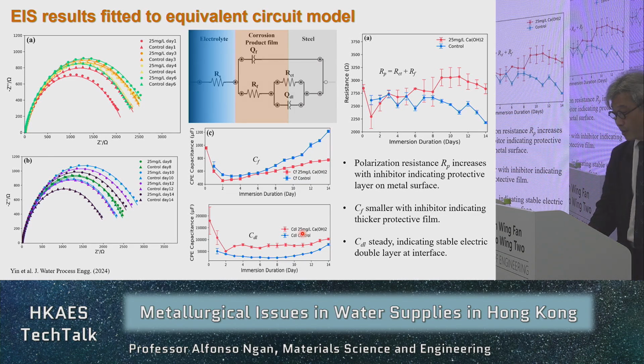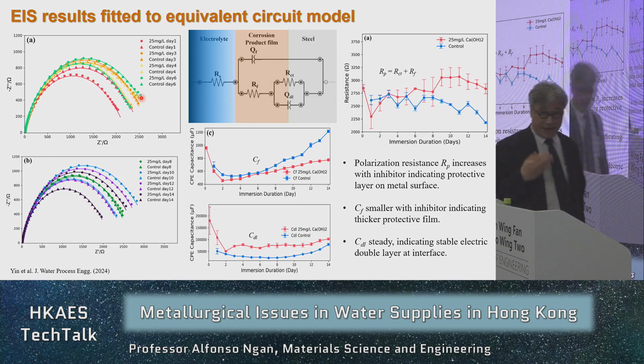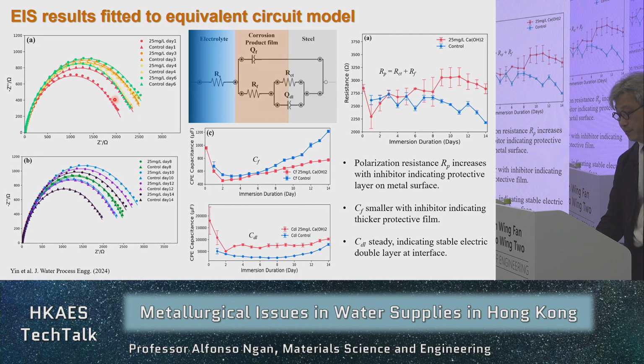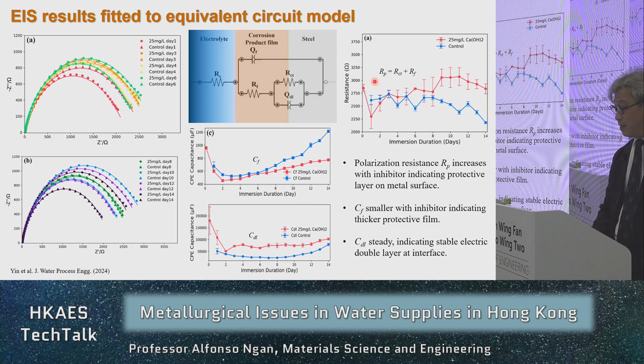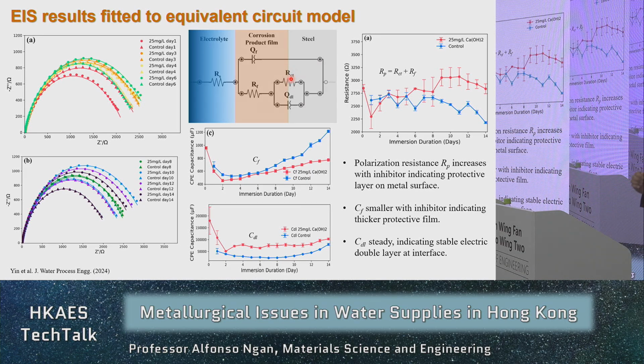Those are the real results from our simulated seawater test. So you see a lot of semicircles, but they are not exactly semicircles. Obviously there will be a strong effect from this redox reaction, but they are not purely semicircles. So some other elements have got to be there in order to explain the shapes of these impedance plots, the Nyquist plots. So just by fitting these parameters, we were able to sort out the so-called Rp, which is the polarization resistance, which is the sum of this resistor plus that resistor, right?